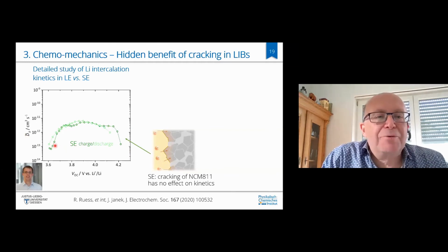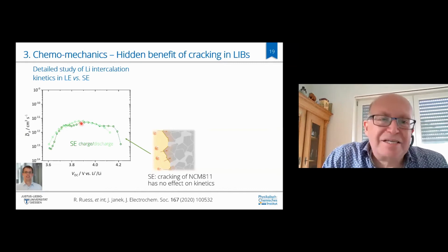And you see now we charge our solid state battery. The chemical diffusion coefficient is increasing, as it always does, and goes down at the end when the lithium content is going down, and this is reversible. So nothing is really changing.